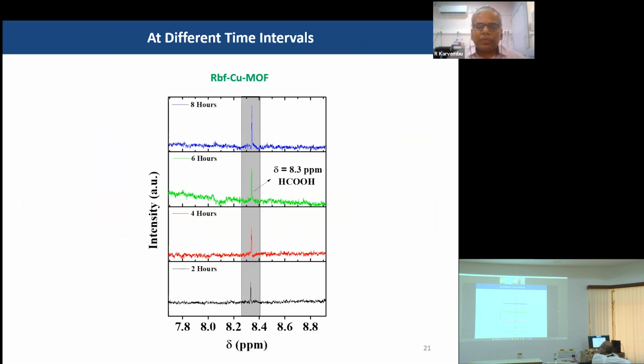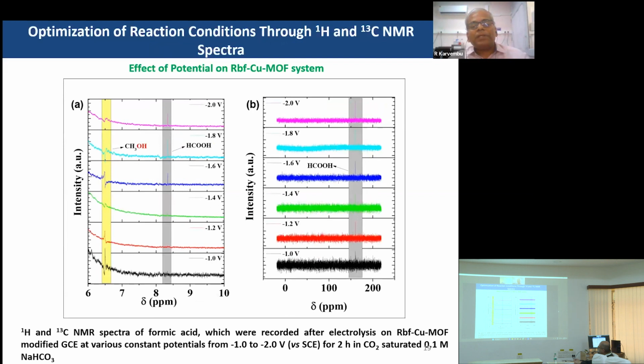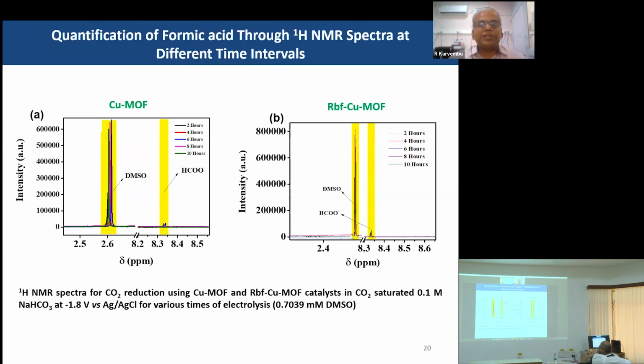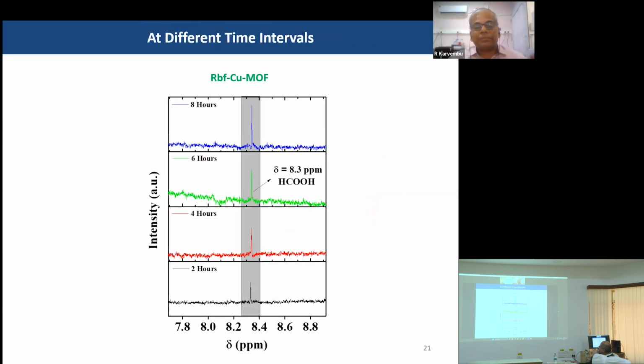At minus 1.8 volts, we collected samples at different times and observed the progressive increase of formic acid formation during the electrochemical reduction of carbon dioxide. There was no much difference in signal intensity between minus 1.8 volt and minus 2 volt, so we took minus 1.8 volt as the optimum potential for the reduction of carbon dioxide to formic acid, and that potential was used in further experiments.